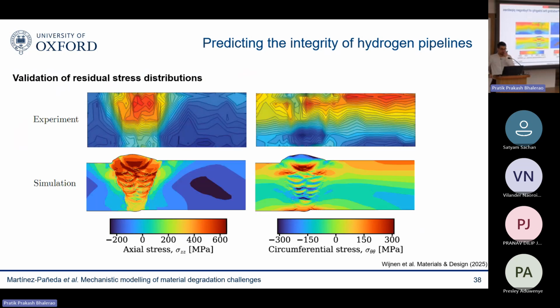The other thing you can validate is against measurements of residual stresses. This is a big deal in the community now. Measuring residual stresses is quite nasty. It's not easy to do. You can see there's a lot of noise in the experimental measurement. This is with X-ray diffraction. But you can see this is for a girth weld.